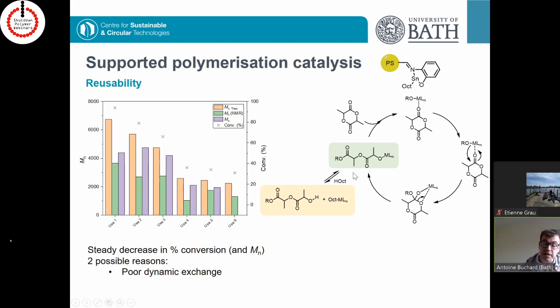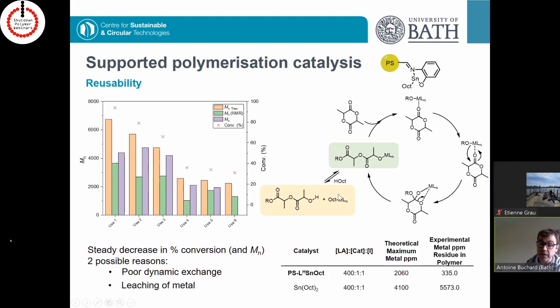And it is very possible that in the end, with our beads, with the type of system we're looking at the minute, we're stuck here so that in the end, we cannot really cleave the PLA growing chain metal bond. Let's say that's one of the hypotheses. The other logical hypothesis is that there might be just some leaching of metals, okay? Which means that while we proceed during the catalysis, some metal species are lost. And in the end, while you reuse those catalysts, then it becomes less and less active, let's say.